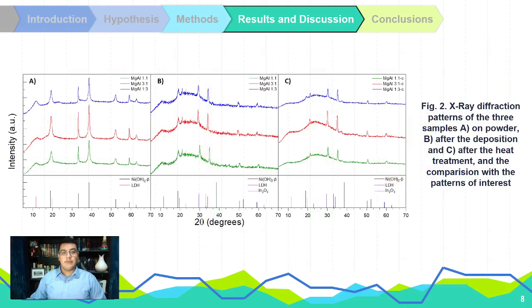Here we present the X-ray diffraction patterns of the three samples, in powder form, after deposition, and after the heat treatment. We can appreciate that once synthesized, our material had both the LDH and the nickel hydroxide phases. This can be due to the low amount of aluminium in the synthesis matrix, which acts as a limiting reagent in the formation of the LDH.